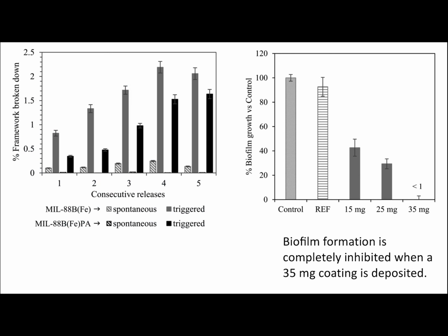Okay, some results that I think are worth mentioning. To the left, we have a chart that analyzes the degradation of the MOF with repeated exposure to that chelator. It shows the difference between spontaneous versus triggered degradation. During exposure to just water, the amount of MOF that spontaneously degraded is super low. Once it's exposed to the chelator, you can see that it degrades. That shows the coating would have a long lifetime, and it does have that triggered gradual release.